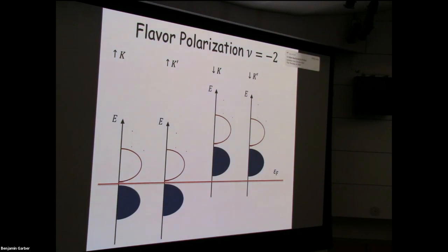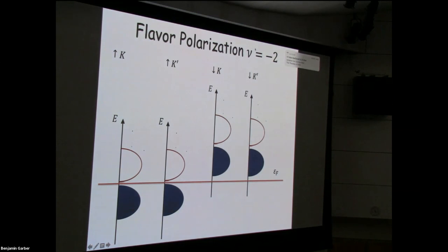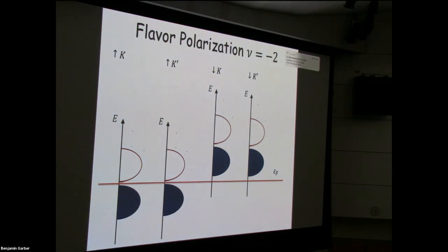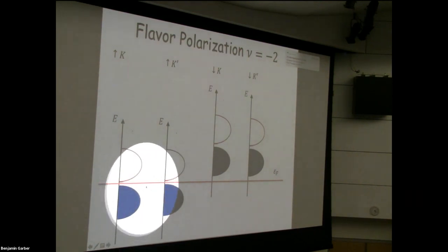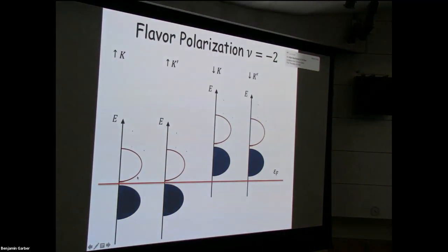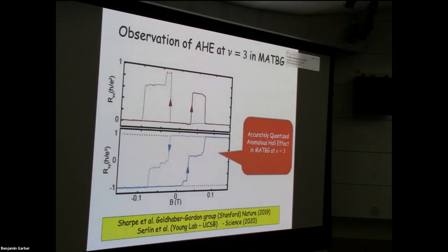okay, so let me just emphasize the observation I just made with this cartoon, focusing on the case of integer filling factor. This is filling factor minus two, so half empty valence bands in this way of counting. I said that what happens is that two of the four flavors are completely empty. And if the filling factor is exactly minus two, that leaves the two remaining flavors as half empty, neutral if you like. And in that case, it's easy to create a gap by breaking an inversion symmetry in the system, and that's how the insulating states are understood.